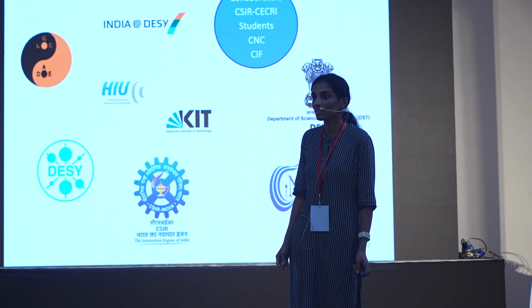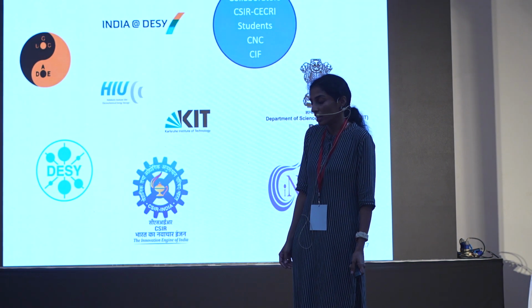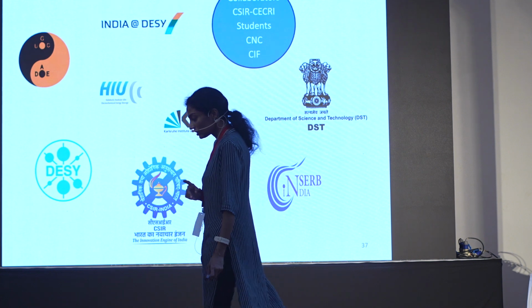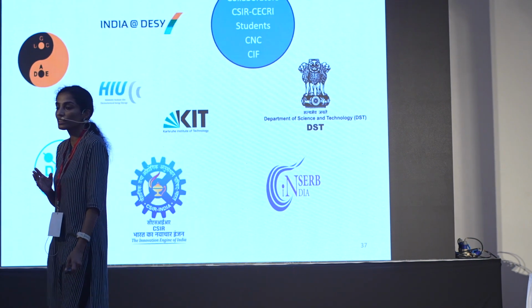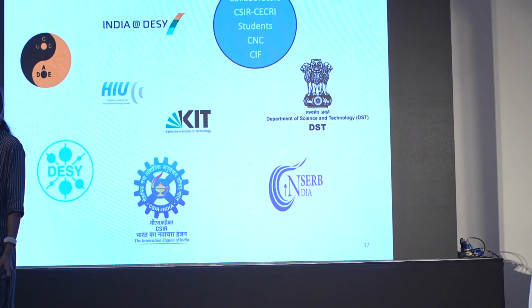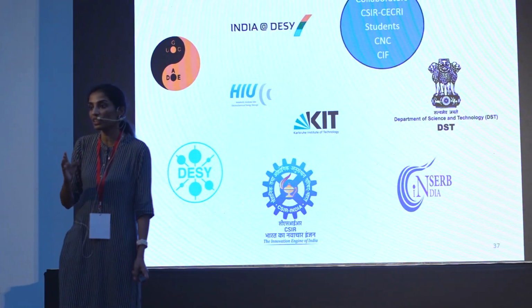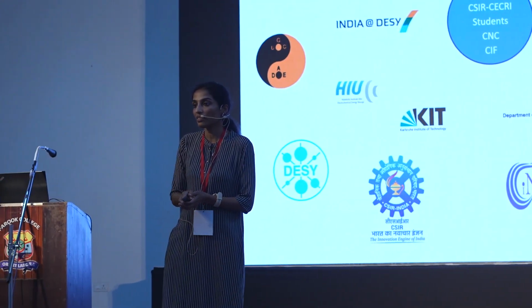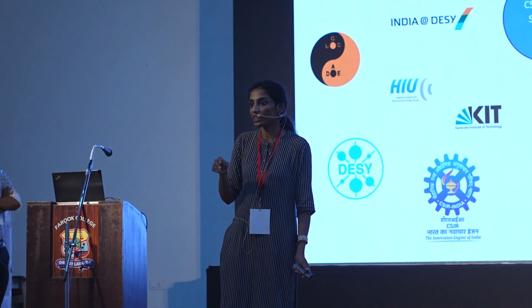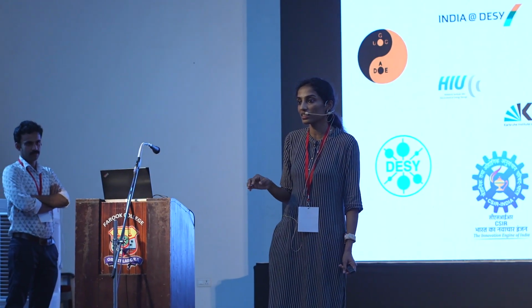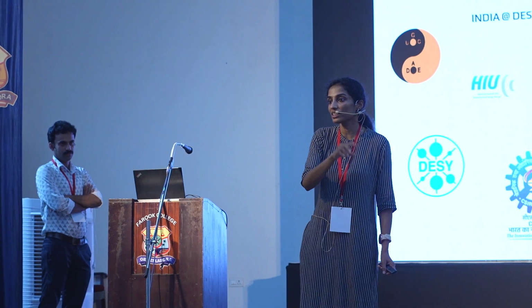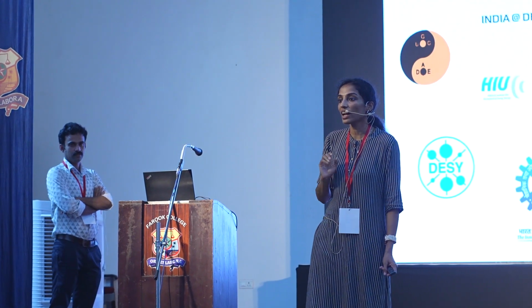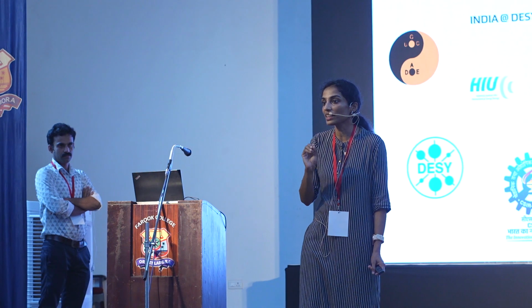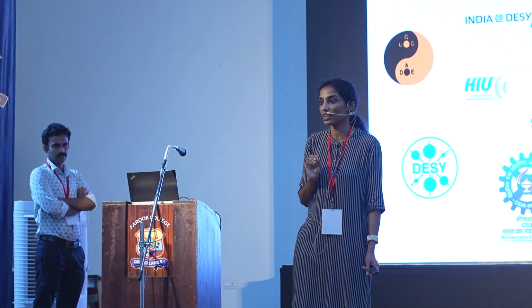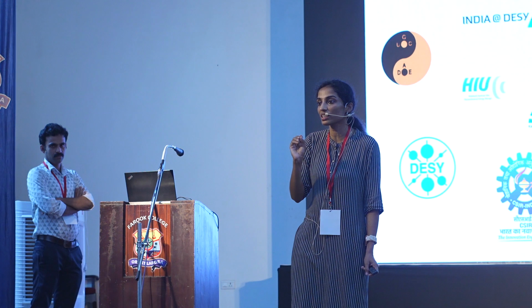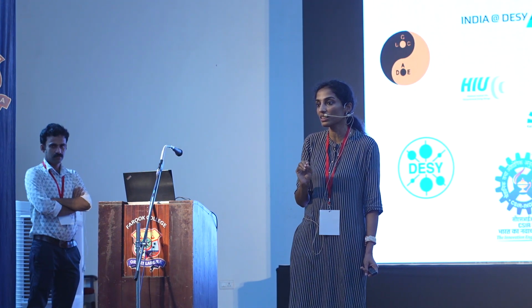So this reversibility is for how many cycles, essentially? You are able to maintain the integrity of the crystal structure. See, normally, if it is not reversible, how will we figure it out? We do CV or dQ/dV for long term. And when I analyze the dQ/dV, the differential capacity plot, after 100 cycles, the electrochemical activity regions remain the same. But I don't guarantee that a percentage of material is not dead. This is very difficult to analyze. If it is a small amount, it is difficult to figure out from X-ray diffraction, and we won't be able to see that.